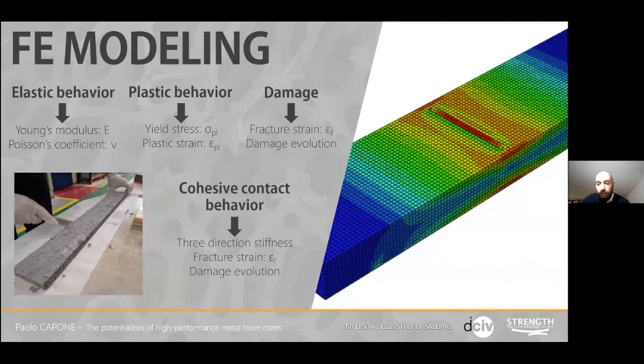The obtained results of the experimental campaign have been used to develop a finite element model using the software Abaqus. Two elements have been defined and geometrically modeled. The first one is the steel skins, and the second one is the aluminum foam core. The model has been performed considering both the elastic and plastic behavior of the materials using the data from the experimental tests, and so defining a Young modulus and Poisson ratio for elastic properties, while yield stress and plastic strain have been defined for the plastic behavior.